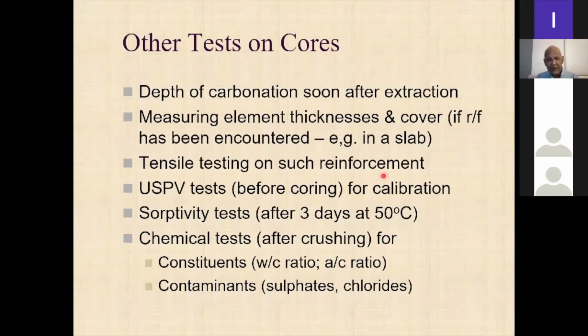Ideally, if you are drilling a slab, say for a 12 or 15-year-old building, instead of avoiding the reinforcement, you should try to cut through a reinforcement, right? Because then you can take that little reinforcement piece out. You can do a small coupon on it and test the reinforcement strength, right? Because like I showed you in that earlier slide, the yield strength of the reinforcement has a big effect on the moment of resistance of the slab.